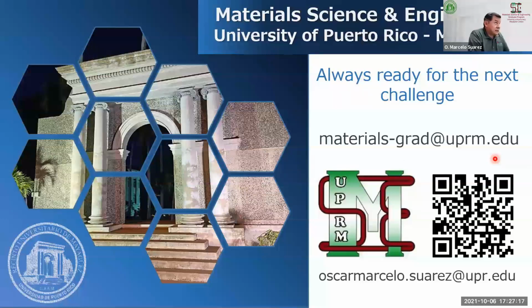Actually, we sent a sample. I don't recall if we sent it to Wisconsin or to UCLA, and they did some TEM analysis of the films. And then they noticed that the aluminum film was not entirely crystalline. It has some amorphization. And we did detect some problems related to that in our diffractometer, the one in 312. That lack of crystallinity in the aluminum film.